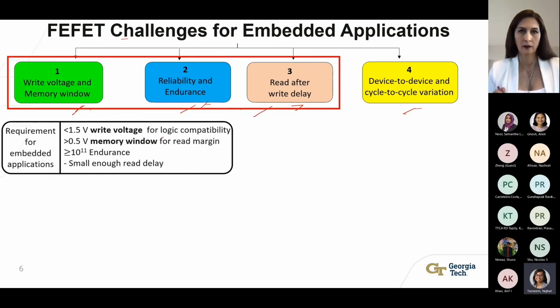For embedded applications and logic compatibility, we need a write voltage lower than 1.5 volts. At the same time, to ensure read margin and immunity to noise and variation, we need a memory window of at least half a volt. Additionally, we require these devices to operate up to at least 10 to the power 11 endurance cycles with a small enough read after write delay. Now, all these challenges are interrelated, but none of them have been fully solved because the device physics of FeFET is still not fully understood, even after multiple studies.